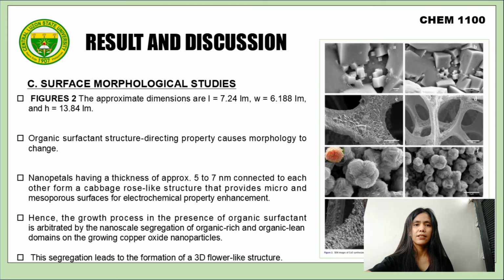Next slide. The first one is the surface morphological studies. Figure 2 shows SEM images of bare and surfactant-assisted copper oxide deposited on copper foam. The SEM images show copper oxide nanocuboid morphology in different sizes covering the entire copper foam skeleton, synthesized without the addition of surfactant. The approximate dimensions are length 7.24, width 6.188, and height 13.84. Simply by the addition of Triton X-100 surfactant, nanocubes turn into nanoflower-like structures.